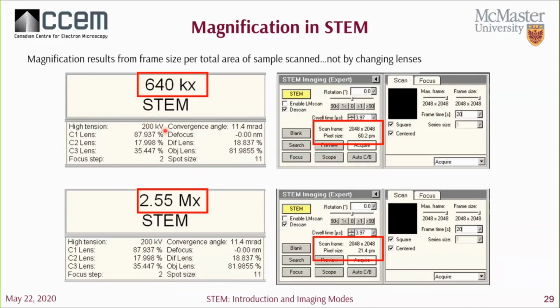And then when you're choosing this, you're going to have to think about what your sampling frequency is. It's a general rule of thumb that you want your pixels to be of a size that's more than double that of your object of interest. So if you want lattice spacing in your images, you need to have an idea of the size of your object of interest, and then adjust your parameters accordingly so that your pixel size is more than double of this size.